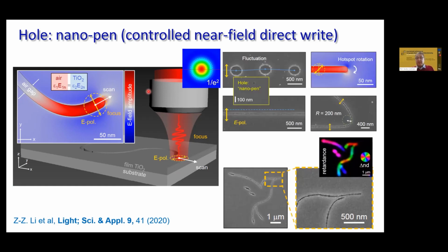So then, by single pulse ablation, you usually create a hole, what I showed before with writing the mask for photonic crystal trapping. There can be subdiffraction limit, but they are still large. They are hundreds of nanometers. But if you are very patient and your laser is stable, there is no problem to ablate what is shown here, this hole, which becomes your nanopen. You make single or double pulse ablation of a very small feature, then you reduce your pulse energy and you just drive the writing on the surface.